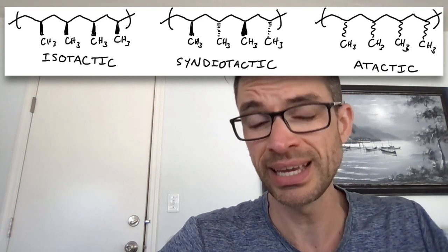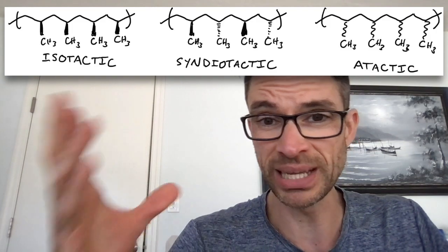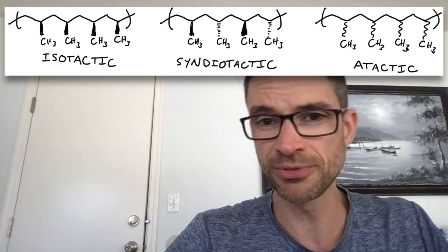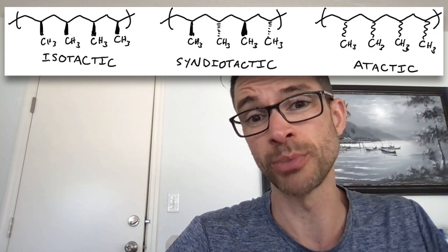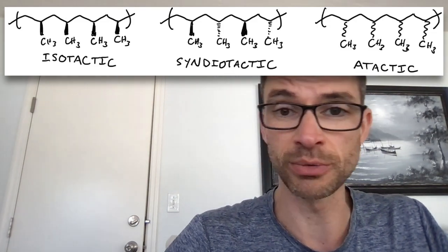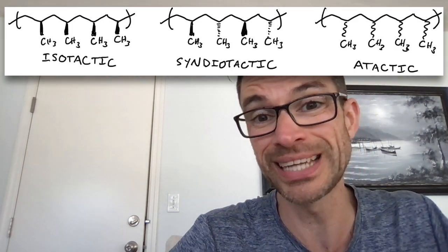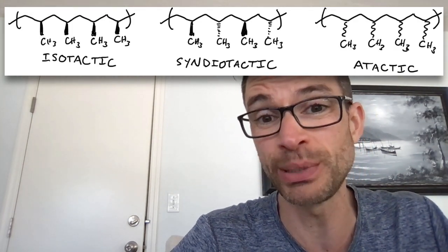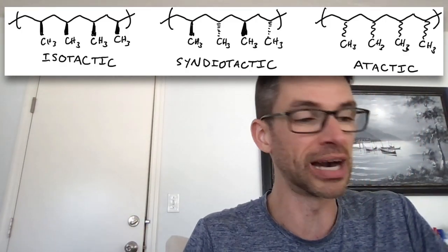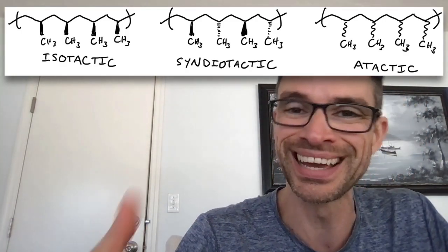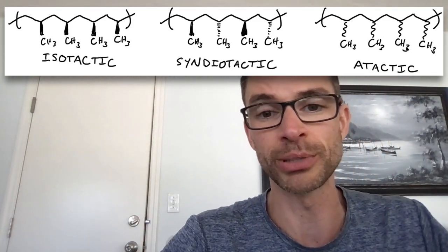Polystyrene has the same sort of thing — most polystyrene is atactic. However, since it has that big benzene group, there are a lot of van der Waals forces, and the material is quite solid and glassy until about 100°C, at which point it gets really gummy and liquefies. It doesn't melt in the thermodynamic sense since it's not strictly a melting transition, but that's when it goes above its glass transition temperature.